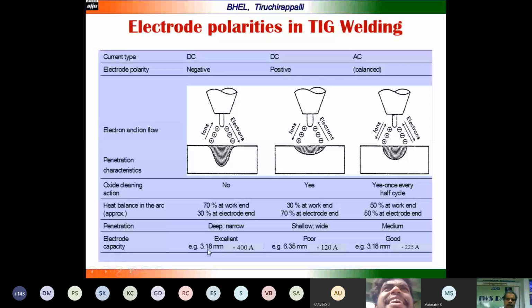Coming to electrode positive, there is a cleaning action, because the electrons are moving away from the job and cleaning the oxide layers over the job, and then the positive ions are coming and making the penetration. Here 30% of the heat is at the work and 70% at the electrode end. Because of that, we are able to get only a shallow penetration and a wider bead width. But look at the current: even with a 6.35 mm electrode, we can use only 120 amps current. That is the issue here.